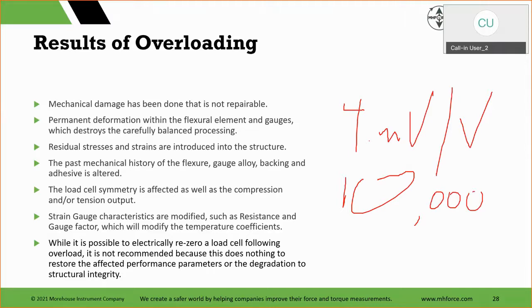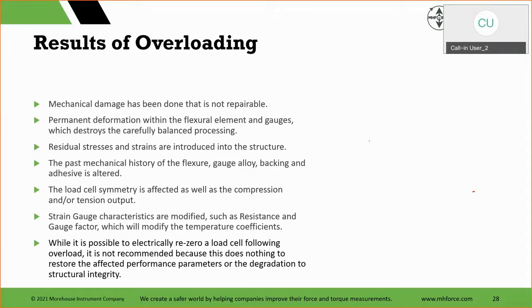That means, hey, maybe in compression now we're reading 10,100, and maybe in tension we were reading 9,900. And same with the millivolts. Maybe we're 3.9 and 4.1. That is a very good indication that someone overloaded the load cell if one mode goes high and the other mode goes low. That's where you want to check and make sure. Use the load cell tester to check the zero balance. There's other meters that can do it if you're out there: Agilent 3458, Fluke 8508. There's a lot of other meters that can check the balance, but those are much more expensive than a load cell tester.